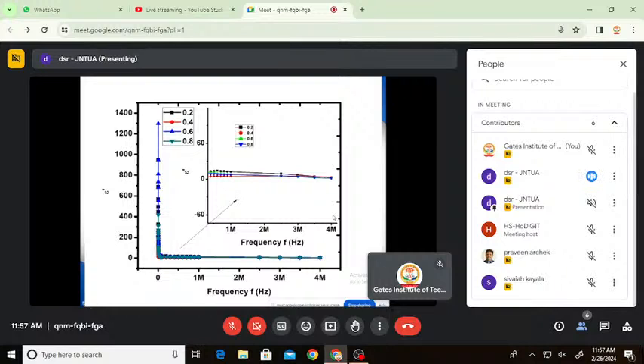Also, grain boundaries exhibit large resistivity while the grains reveal low resistivity. So, as a whole, the inhomogeneous dielectric structure is accountable for this nature of dielectric constant and dielectric loss with frequency. The high dielectric loss values are observed at lower frequencies, whereas the smaller dielectric constant values are noticed at high frequencies. A similar trend was observed in the dependence of dielectric constant on frequency for all compositions. Hence, at higher frequencies, all these samples may ensure substantial contribution as dielectric absorbers.